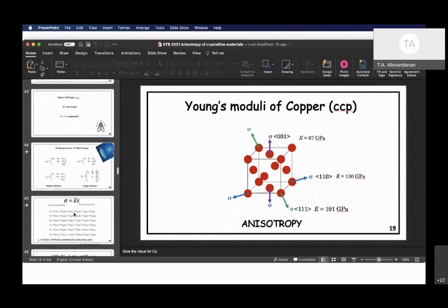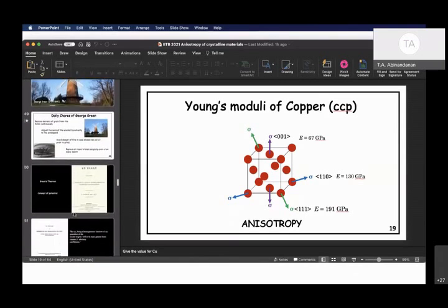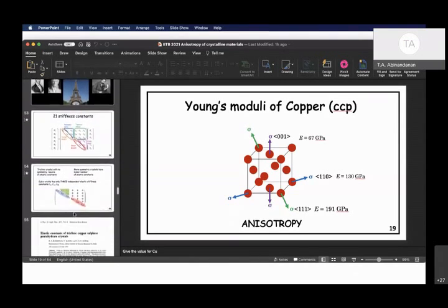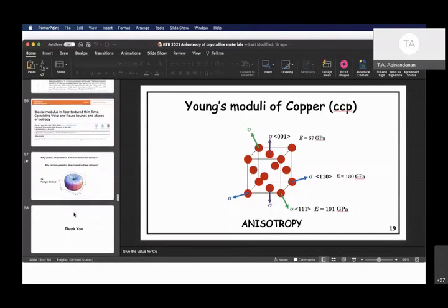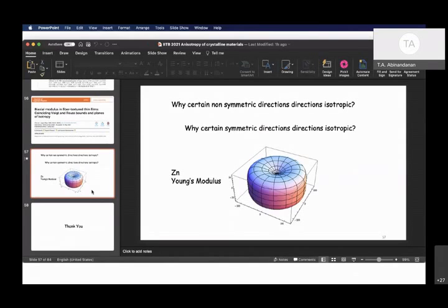How are you? Your argument is not going to take you very far if you are going to look for the physical reasoning for isotropy or lack thereof. It's the property of the fourth rank tensor. Right now you are talking about the elastic modulus tensor, but any property which is described using this kind of symmetric fourth rank tensor with 21 independent components, if you apply crystal symmetry, you will find this to be the case. So yes, it is contained in the mathematical entity which is this fourth rank tensor.